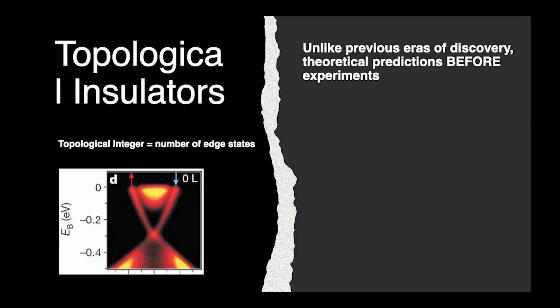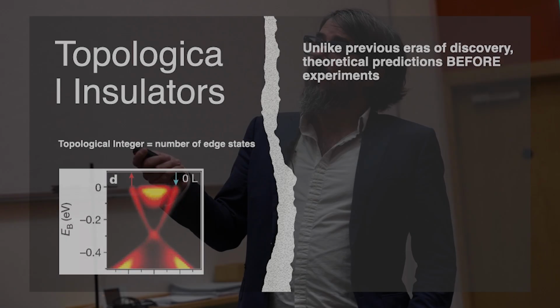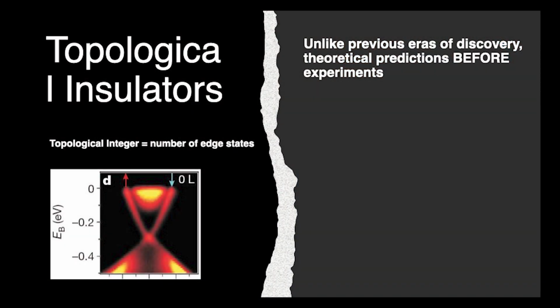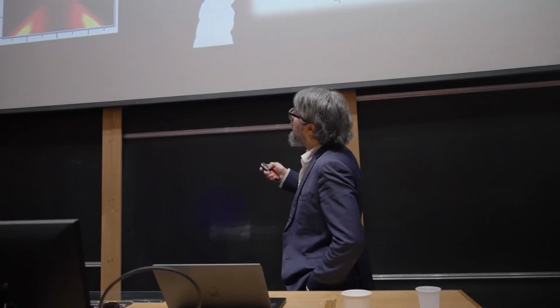Now, in the modern bulk boundary correspondence, this is something that's true across the board, and it is in topological insulators. And for example, here you have a quantum snapshot of bismuth selenide. This is a snapshot of the electronic states of bismuth selenide. You can see here some blobs, which basically means that you're looking at the bulk of the sample. There's a lot of electrons here, so you're looking at the bulk. But the quantum snapshot is taken by cleaving the material and looking at the surface. And when you look at this surface, you see these edge states here, which are very clearly shouting at you. And their number, mod 2, is the topological invariant that describes this phase.